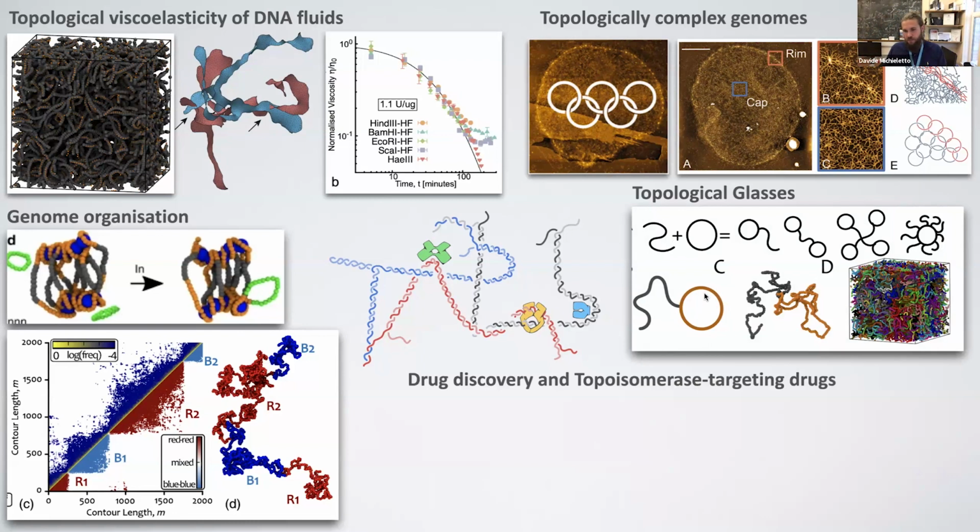And these were actually made with polystyrene by a Japanese group, and they're quite interesting because then what happens is that these tails can thread through the head of these tadpoles, and then if the tail becomes long enough, you have so many constraints that the tadpole that is threaded cannot relax its conformation, but that tadpole that is threaded is also threading another one, and so there is a proliferation of constraints which eventually create a glass,